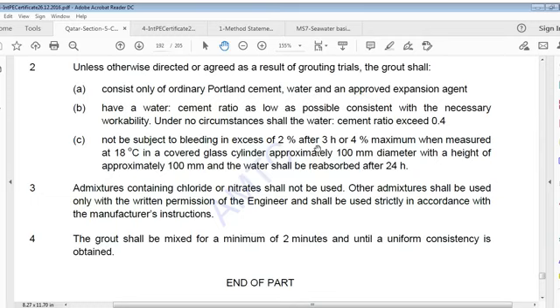Grout shall not be subject to bleeding in excess of 2% after 3 hours or 4% maximum when measured at 18 degrees Celsius in a covered glass cylinder approximately 100 mm diameter with a height of approximately 100 mm, and water shall be reabsorbed after 24 hours. Admixtures containing chloride or nitrate shall not be used. Other admixtures shall be used only with written permission of engineer and used strictly in accordance with manufacturer's instruction. Grout shall be mixed for a minimum of 2 minutes and until a uniform consistency is obtained.